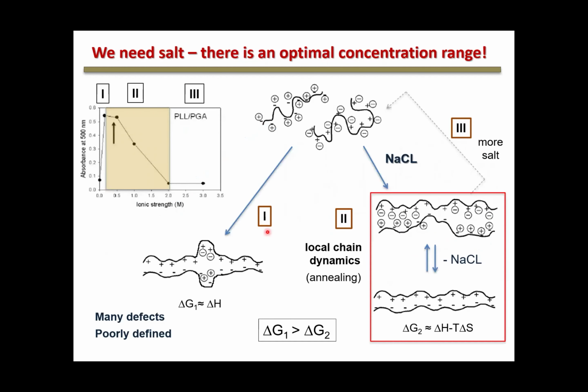And in this interaction, concentration of salt plays a crucial role. If you add very little salt, here this is the ionic strength, you have the formation of polymer complex, but this is very defective. It's just a one-way process. They don't go apart, and you can hardly control the interaction in this polymer complex. If you add too much salt, like here, more than, let's say, 2 mol per liter for this particular polymer pair, then they don't interact, they go apart, basically. And if your concentration of salt is kind of optimal, which would be the specific range of concentration for each and every polymer pair,